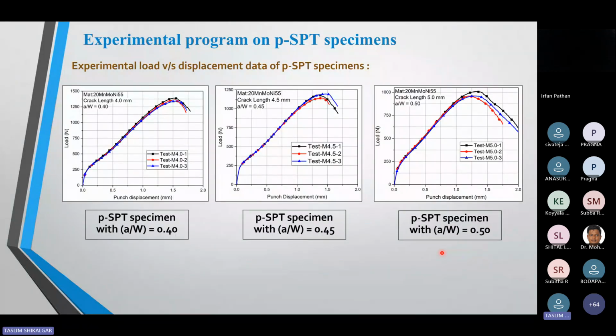I tested different crack length specimens. Here I just mentioned this a by W. I tested these 3 a by W ratio crack length specimens. I tested 3 specimens per crack length because I want to see the repeatability. Repeatability is the most important challenge to achieve. Because if you are not getting repeatability during each test, then these results are not useful to get any correlations in the future. So I wanted to check the repeatability of my test results. So I got the repeatability.